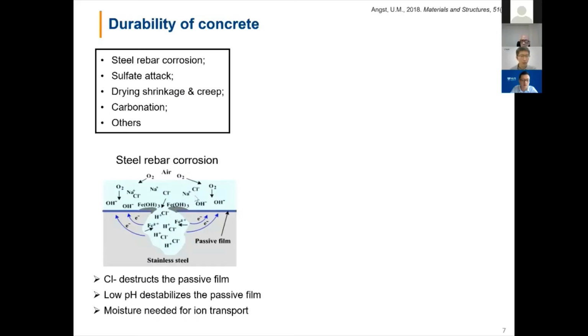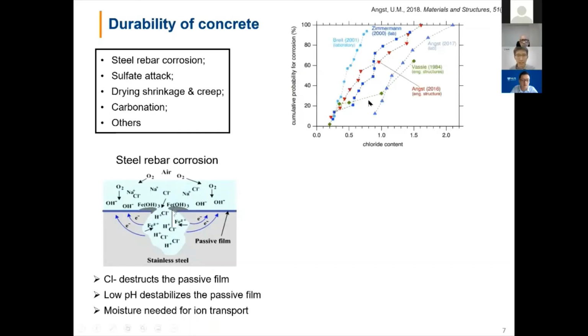However, if the pH value of the concrete drops, or if we have chloride penetrating into concrete, they will destroy this passive film, and they will result in an active corrosion of the steel rebar. In many standards, they define a concept called critical chloride content. That means when your concrete contains a critical amount of chloride, we will consider the rebar to be in danger of corroding. However, different researchers have reported very different values for this critical chloride content. Some researchers say that if you have chloride content of about 0.8%, then your steel will corrode. But others said that the critical chloride content can be as high as 2.1%.